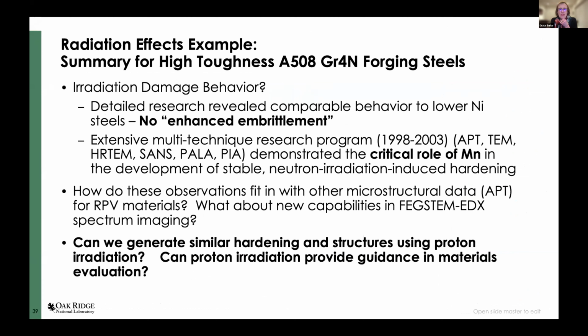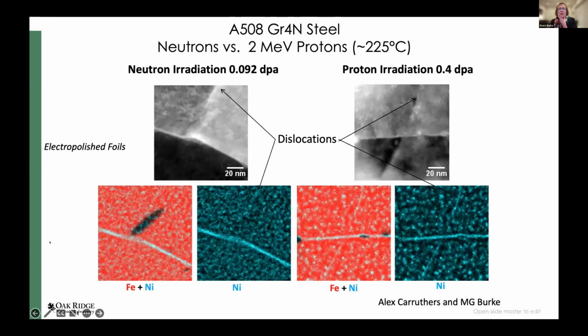Well, how about fitting in with other techniques? And what can we do now that we couldn't do back in 2003, 2004? And how about generating similar damage features? Could we do that with proton irradiation? Let's check. Great. So here is an example of neutron irradiated damage. This is looking at A508 grade 4N steels, about 3.4 weight percent nickel, and proton irradiated steels. This is a bit higher DPA, with some HAADF images, and then looking at nickel partitioning.